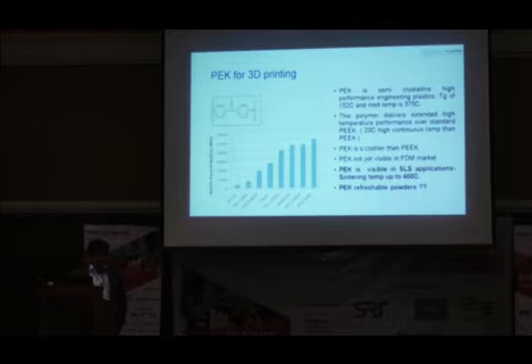Another material is PEK. You have only one ether, polyether ketone. So you can see this material is also similar to PEEK, but it has 20-degree higher continuous temperature than PEEK. So when you are using PEK, you can withstand 260 degrees centigrade continuous temperature, only with the unfilled material. And when you use this material with carbon fiber, you can go up to 320 degrees C continuous temperature. So that is amazing about this material.